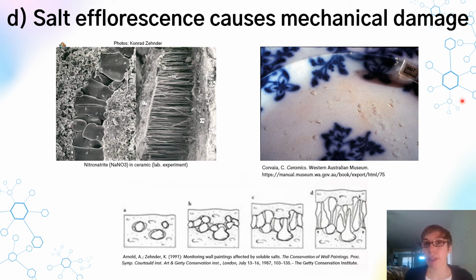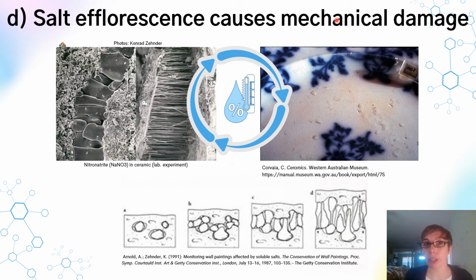And in environments where the humidity is uncontrolled and fluctuates a lot, you can end up with repeated cycles of deliquescence and efflorescence, which over time cause serious mechanical stress to build up in the artifact and can lead to some pretty catastrophic damage. This type of physical damage is the biggest threat posed by soluble salts for a lot of materials, things like ceramics and glass, and most organic materials like wood and bone and ivory. Even though, as we've discussed, chemical damage can also attack and affect them as well.